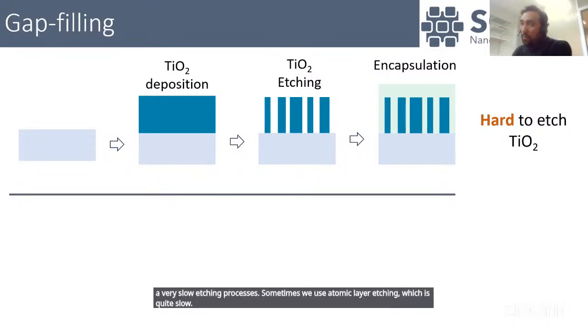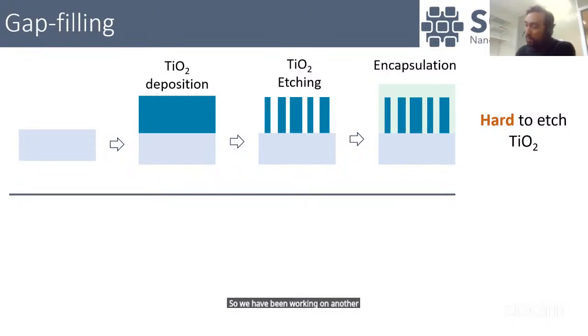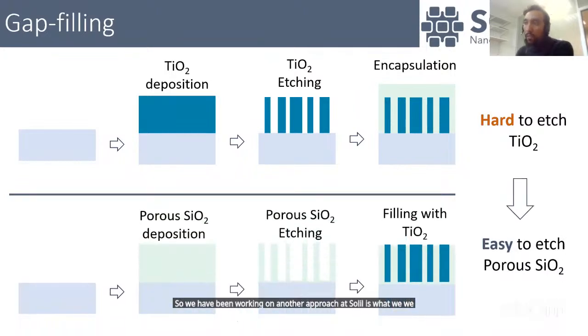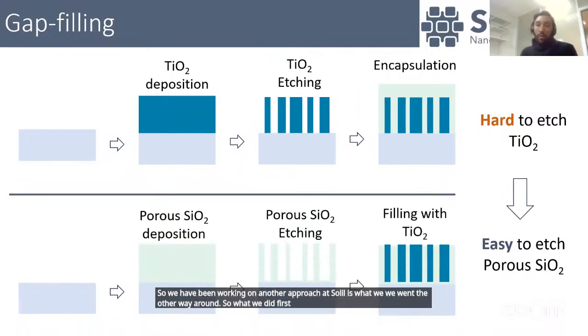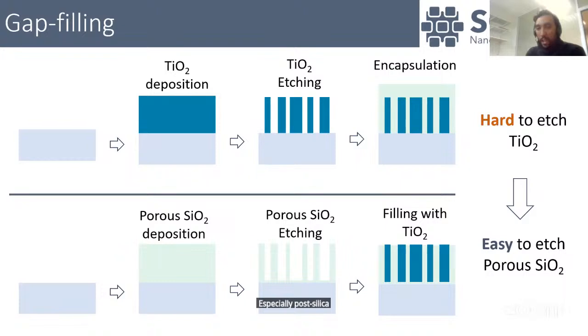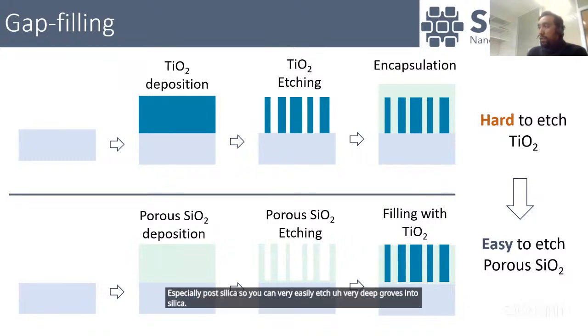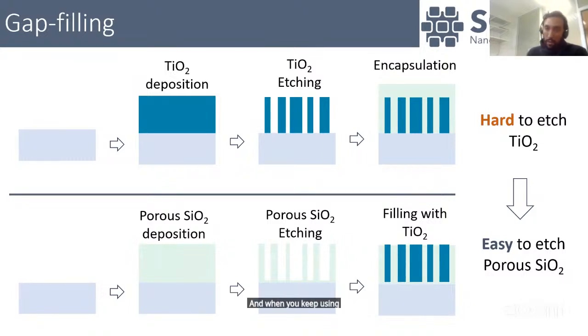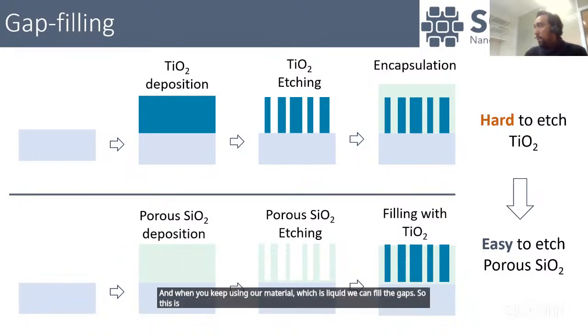So we have been working on another approach at Sol-nil, where we went the other way around. What we did first is, can we just, because our materials are liquid, make holes in silica, because silica is very easy to etch, especially porous silica. So you can very easily etch very deep grooves into silica. And then you keep using our material, which is liquid, to fill the gaps. This is what we have been working on for the past year.